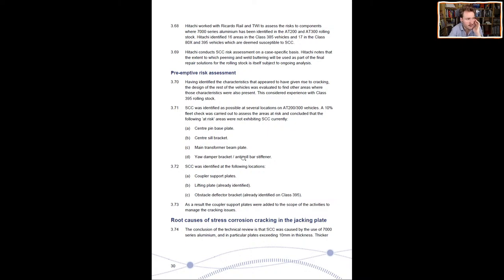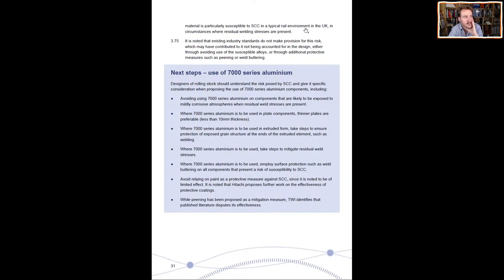So actually, I wonder if there's a combination. Well, they didn't identify a combination, but that potentially could be a combining factor to get even faster fatigue cracking there. So the root cause of stress corrosion, the conclusion was that this was caused by the use of the 7000 series aluminium, and in particular, plates exceeding 10 millimetres in thickness. Thicker material is particularly susceptible to stress corrosion cracking in a typical rail environment in the UK, in circumstances where residual welding stresses are present. So you get the residual welding stresses, soggy, salty air, and then combine that with the 7000 series material. That's our triangle there, isn't it?